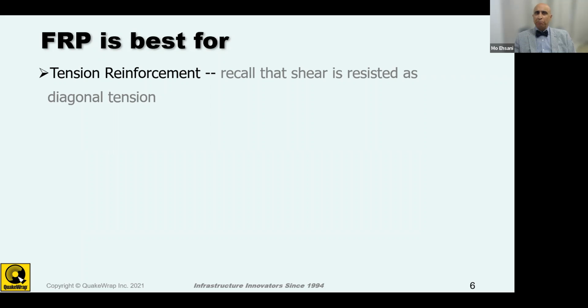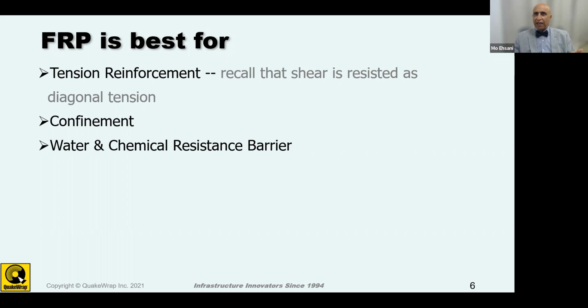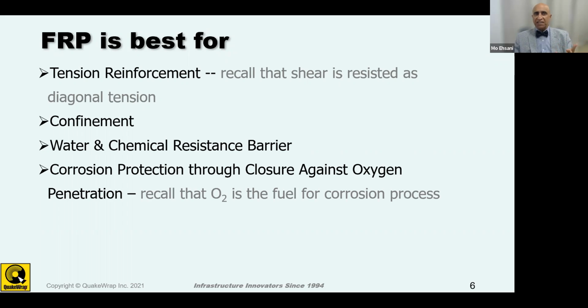FRP products are best as a tension reinforcement for structures. And remember that in concrete structures, we also design them as a tension element to take the shear. They are also ideal for confinement, like wrapping them around a column or a wall. And they have excellent water and chemical resistance. And remember that for corrosion protection, they create an impervious layer around the structure. And that way, by preventing oxygen from penetrating through that barrier, we extend the life of the structure significantly.